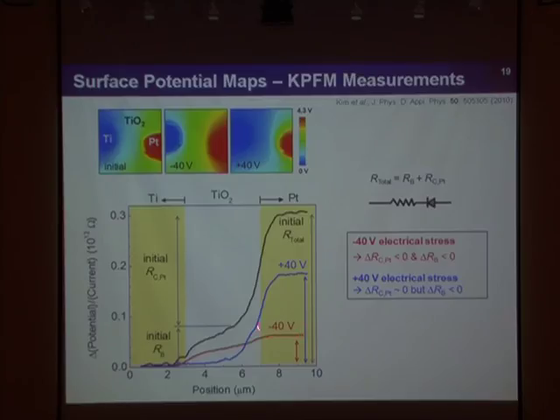After applying minus 40 volts, there is a significant decrease of the contact resistance as expected. In the plus 40 volt case, the contact resistance doesn't change quite a lot. However, we can observe quite a big change in the bulk resistance. Actually, even for the minus 40 volt case, there is a decrease of bulk resistance. So the issue is how to explain the bulk resistance change.